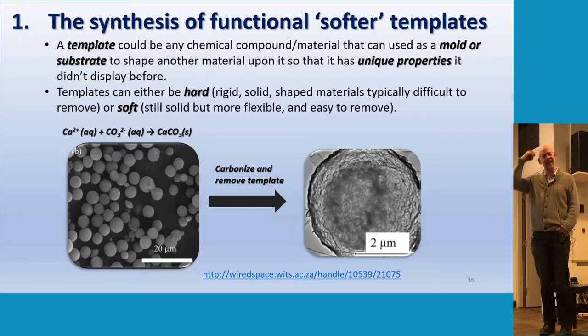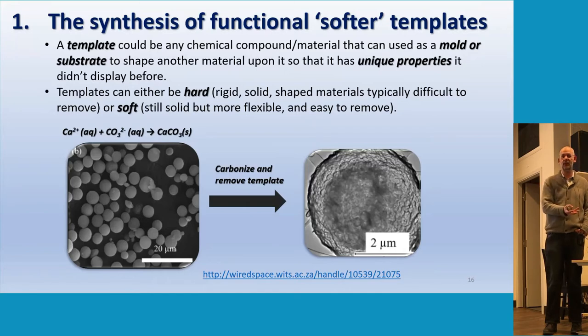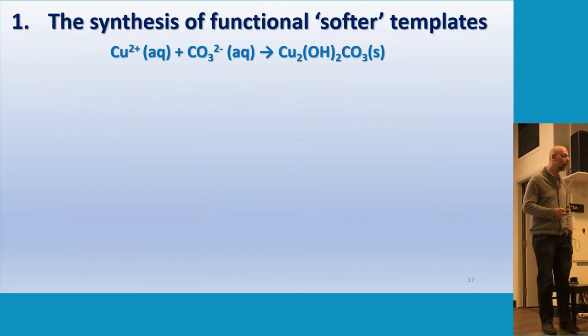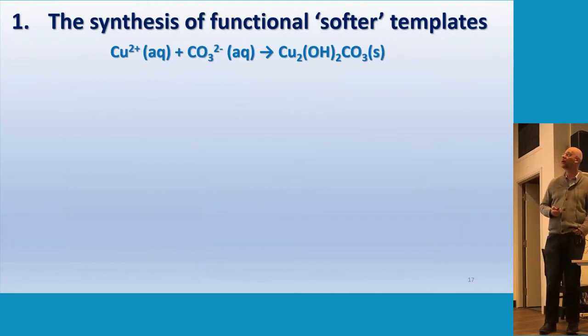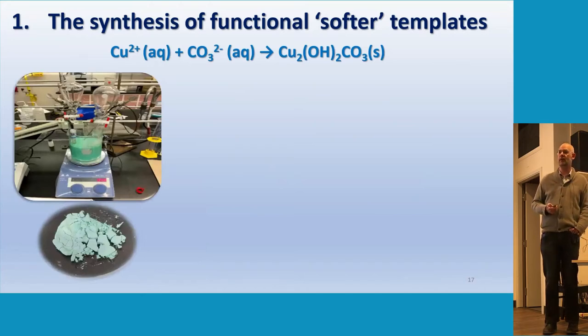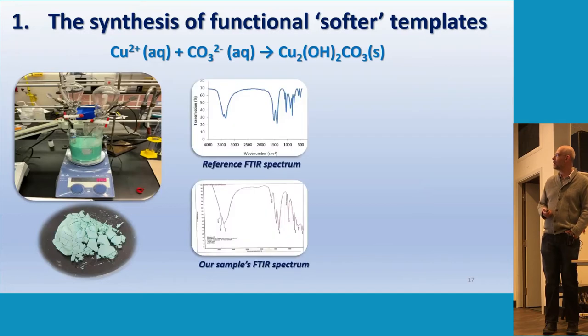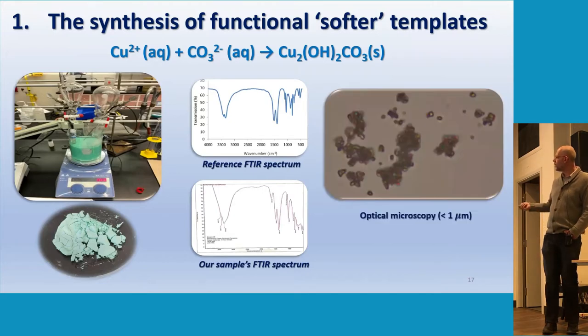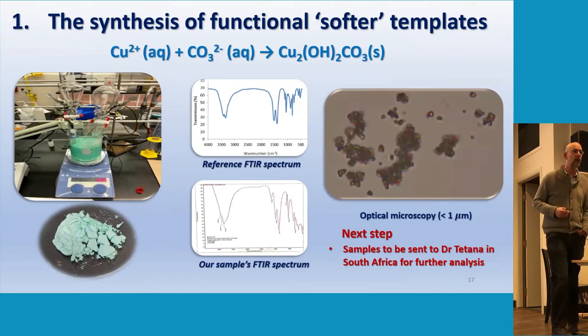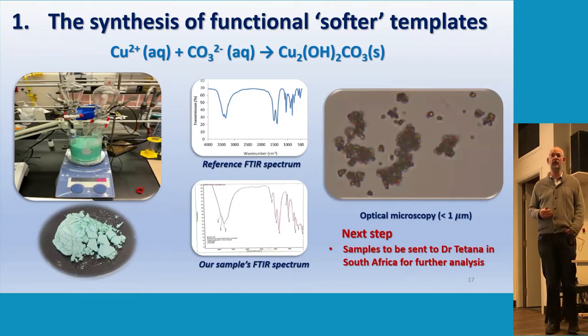We were thinking, well, it's kind of wasteful. You make a template, cover it with carbon, and then you get rid of the template. What if the template could be something that's useful? And the carbon, something that's useful. So we've moved towards looking at copper templates. And this is copper carbonate. We've already done this in the laboratory, so we're still in the early stages. We've made the copper carbonate. We've characterized it relative to a reference, so we know that we're making what we think we're making. And we're getting particles that are less than a micron in size. These are clumps. Of course, this is optical microscopy. So our next step would be to send these samples to South Africa, where we'll be using electron microscopes to actually look at the samples, see what their actual sizes are, and get a sense of what we've made.